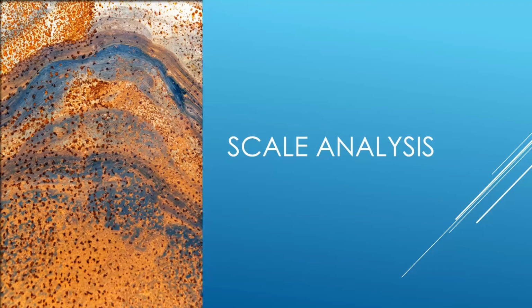So on a scale analysis, normally we would just scrape the surface. That's all you do. You don't have to worry about doing anything fancy. But on this one here, sometimes you have to do something a little bit different. And the reason is if I have a fracture, I don't want to scrape the surface to get that corrosion product off, because now I destroy that fracture. And sometimes for litigation, they won't allow you to scrape the surface either. Strangely enough, they allow you to take a replica off the surface and take that scale off, because that does destroy it too, but they don't seem to think that's destruction.